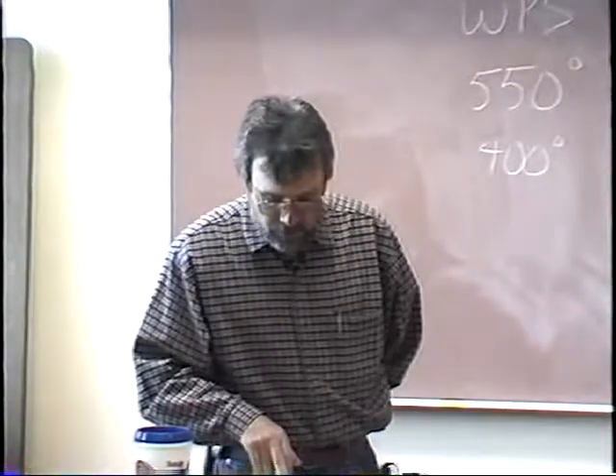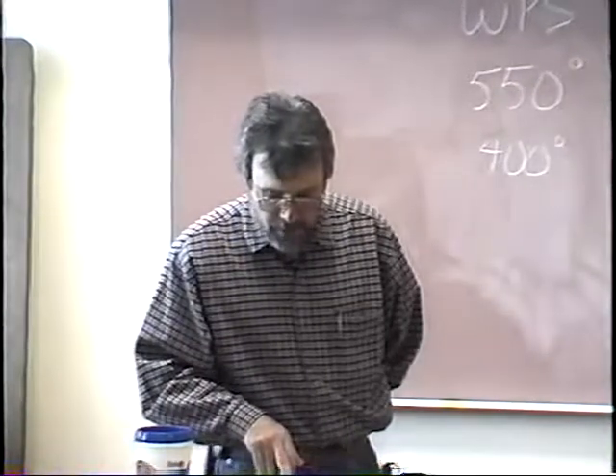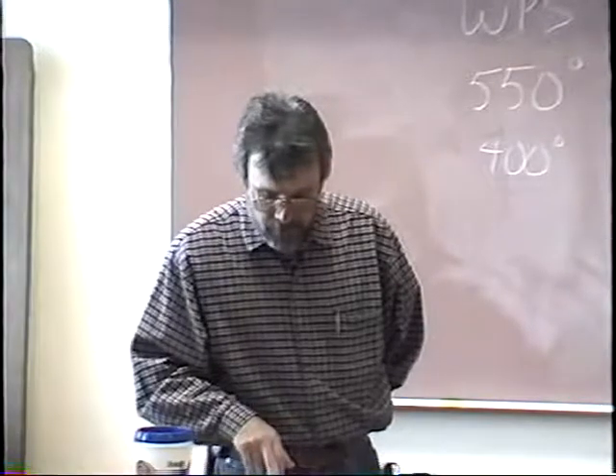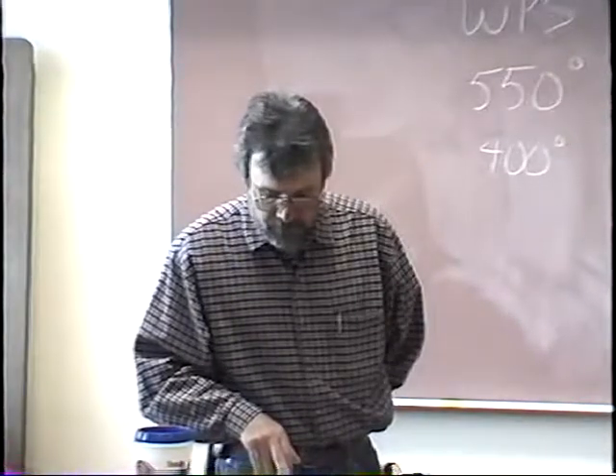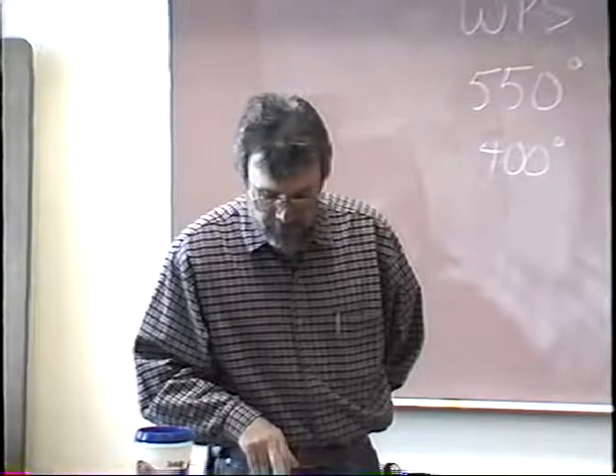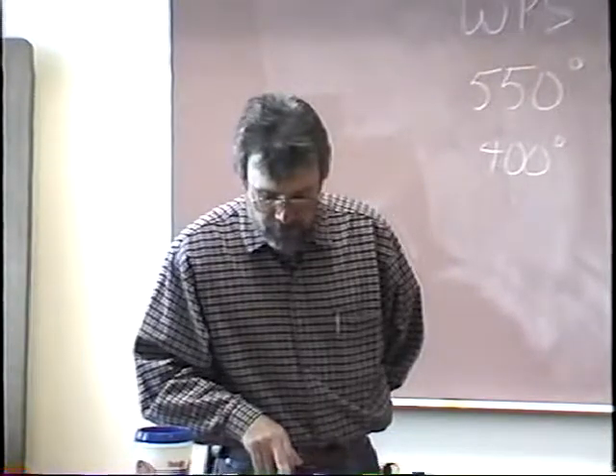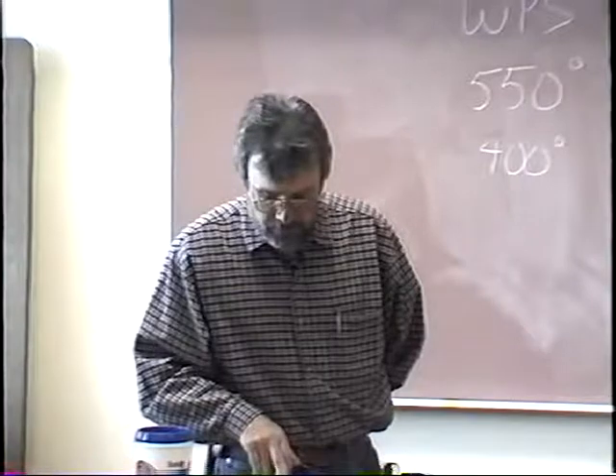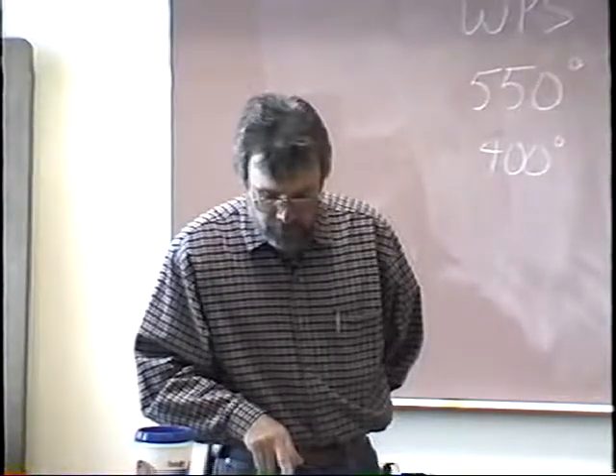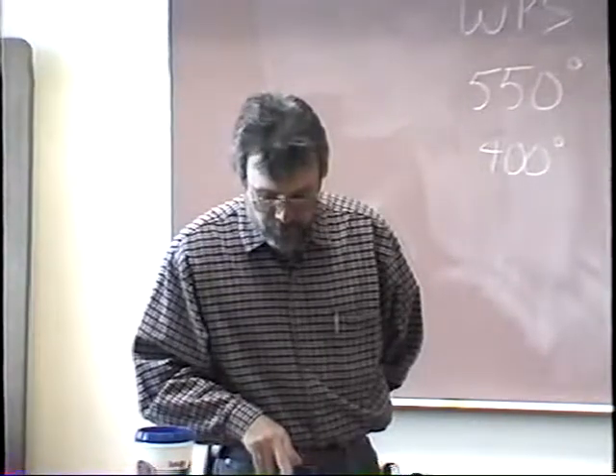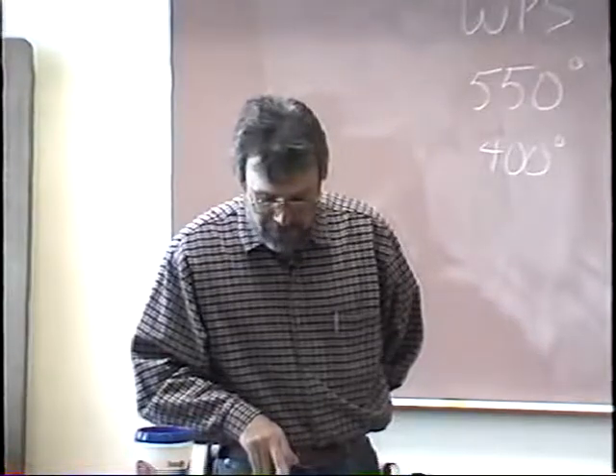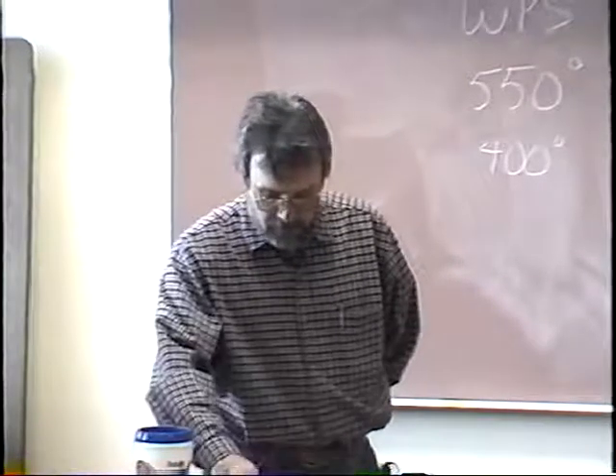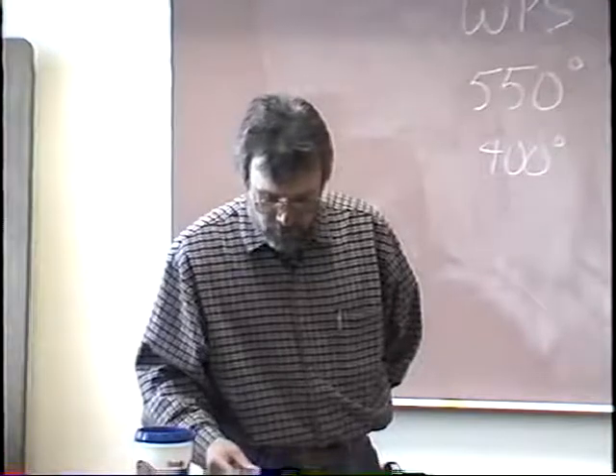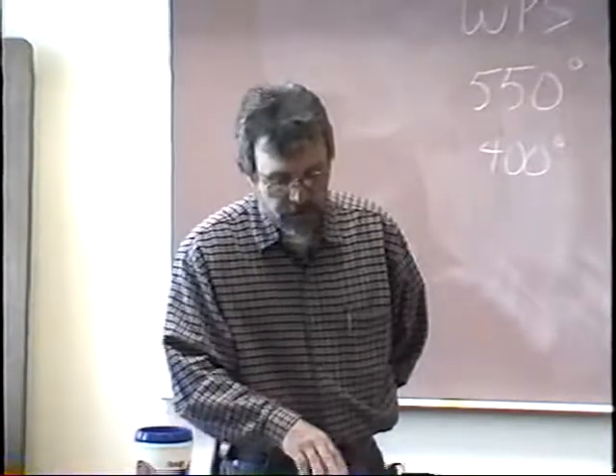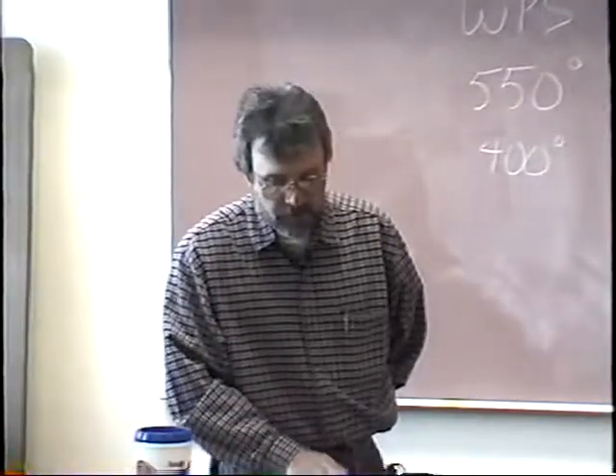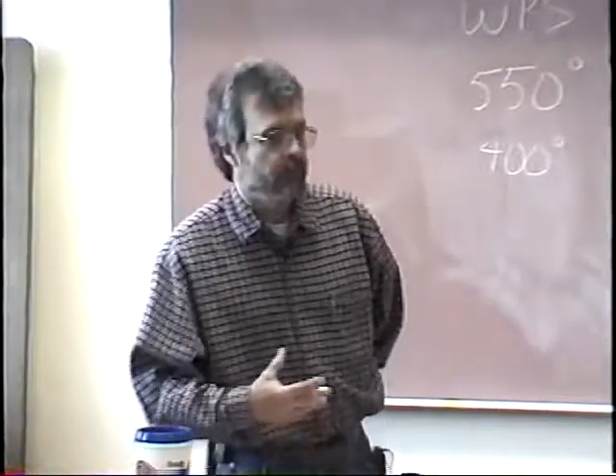When working with an alloy steel, the interpass temperature has an effect on grain refinement of the weld metal. The time between beads affects the extent to which the grain size is defined. Depositing weld metal immediately after another may result in no grain refinement of the weld metal. Allowing the previous bead to cool to room temperature before depositing the next bead will yield less grain refinement than depositing the next while the previous one is still hot, but below the critical range. The significance of refining successive weld beads is reflected in the notch toughness impact value.